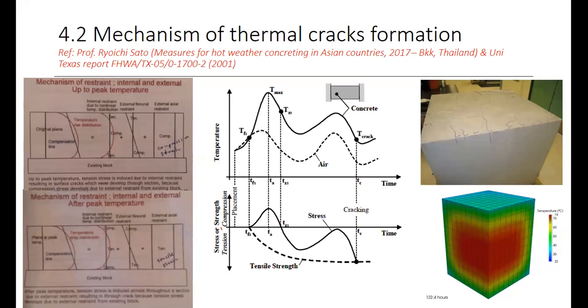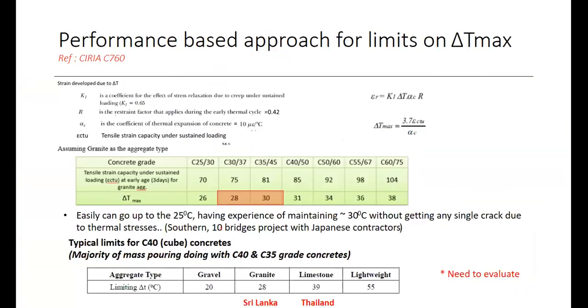So if we can manage those tensile forces, which could arise due to the high amount of heat dissipation, we can eliminate the thermal cracks. That is why there is a limit for the maximum temperature, because the temperature gradient is the driving force. We know that Q, the amount of heat transport, is proportional to the temperature difference between two edges, like the current is proportional to the voltage difference, a similar thing. The temperature gradient is the driving force of that heat. If we can reduce that driving force, we can reduce the heat generation.